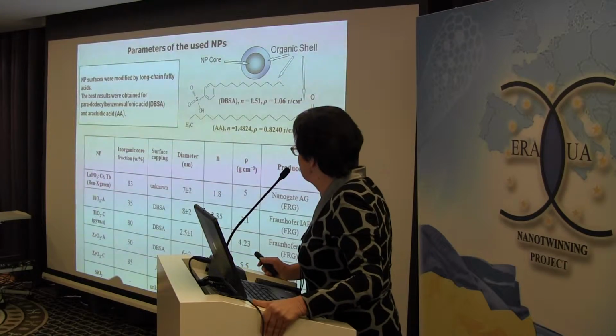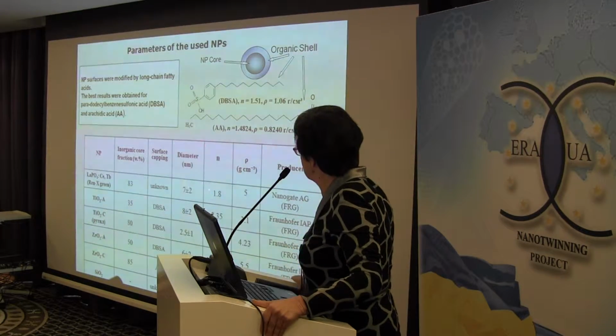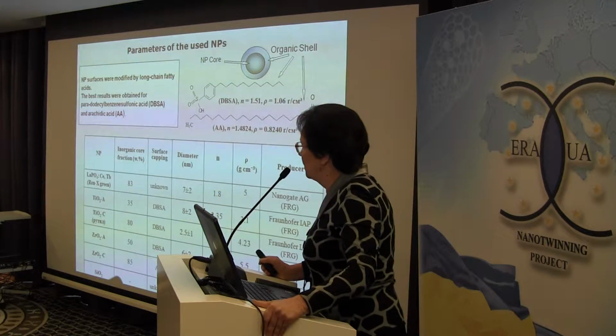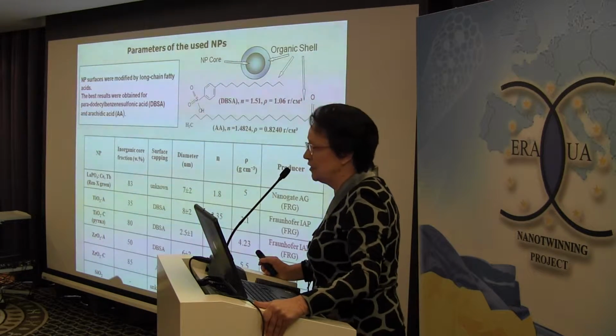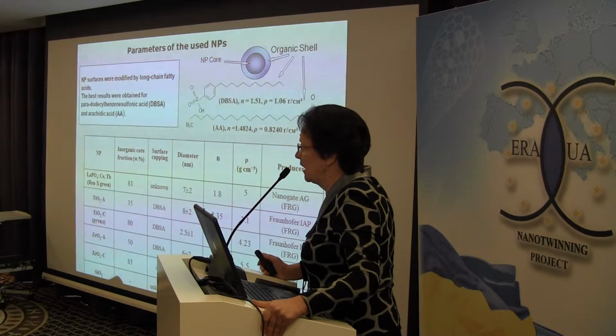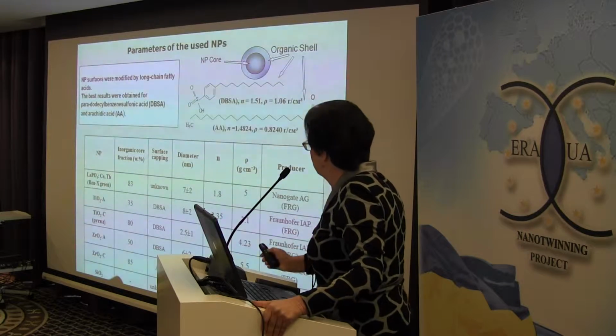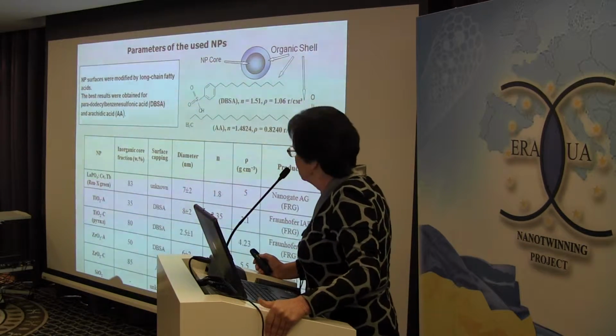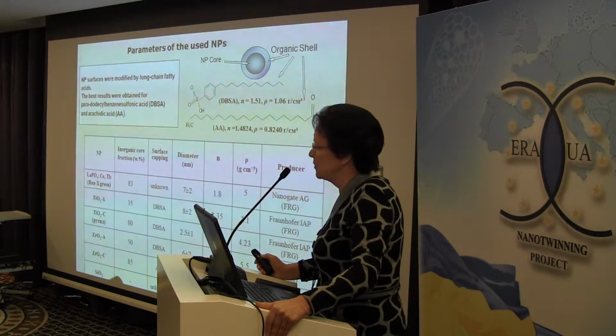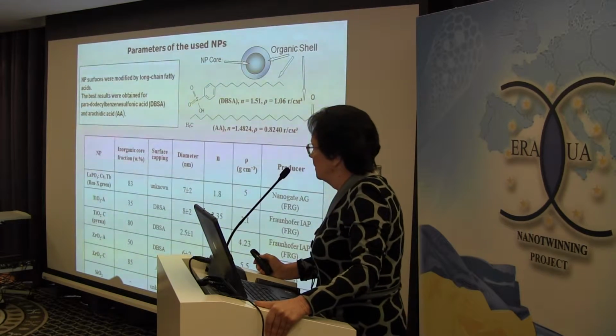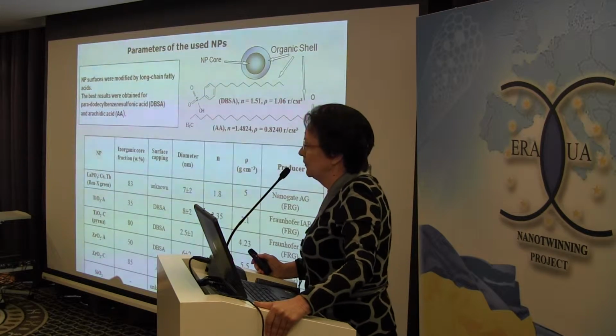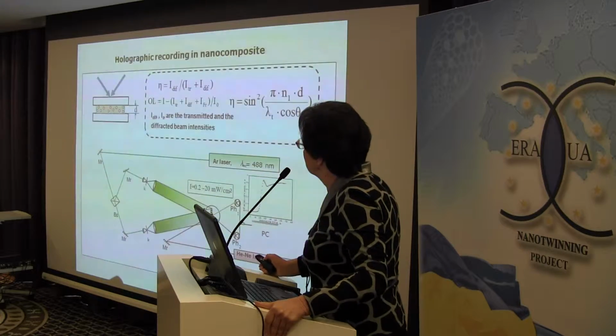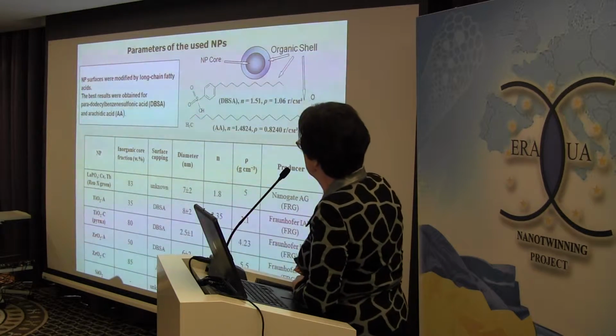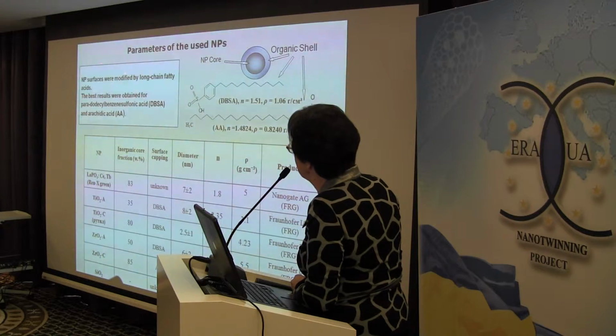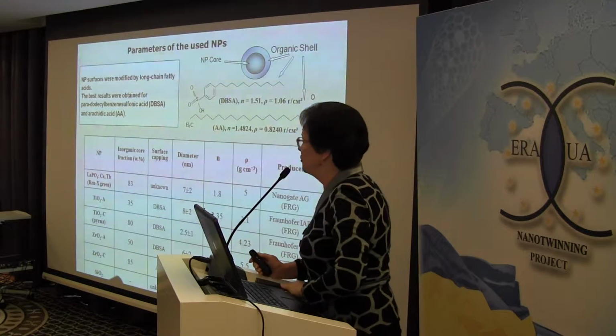The refractive indices of nanoparticles must be larger or smaller than the refractive index of the polymer matrix to provide the high contrast structure. To ensure the compatibility of inorganic particles with the polymer matrix, their surfaces were covered by an organic shell. Nanoparticle surfaces were modified by long-chain fatty acids.